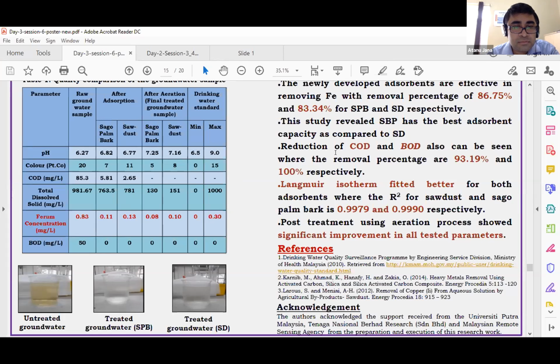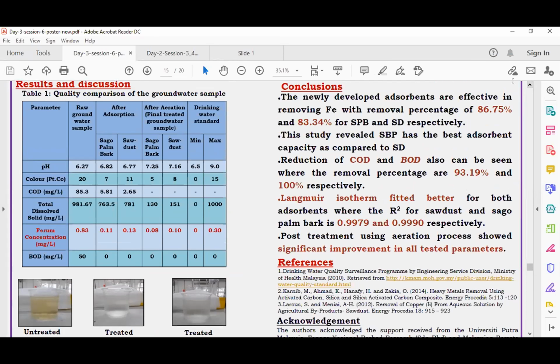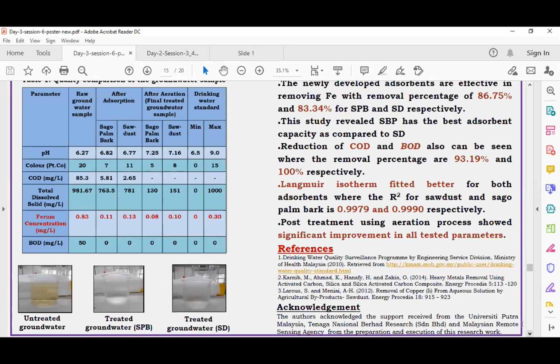The conclusion for this study is we have found that the newly developed adsorbent managed to reduce the pollutant by more than 83% for both adsorbents, and the same findings also happen for COD and BOD. We did conduct a study on the Langmuir isotherm. We found that this is the isotherm that fits well to our adsorbent. So I think that's all for my presentation.